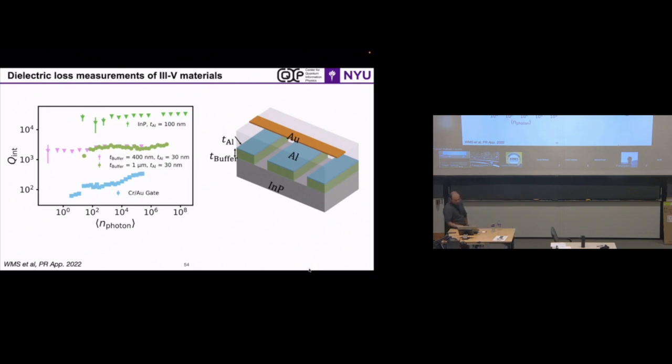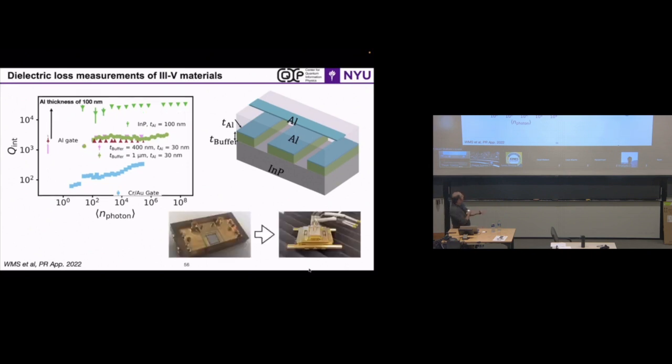Let's change that gold to aluminum. We switched to aluminum, we get our baseline. That's great. Then it's like, so why is this one different than that one? Is it just because I'm growing material? And the student said, this is 30 nanometer, that's 100 nanometer. Maybe that's the difference, because the participation that you get from 30 nanometer is different than 100, and indeed it went back up to basically the baseline of indium phosphide. So one of our biggest challenges now is moving away from indium phosphide.